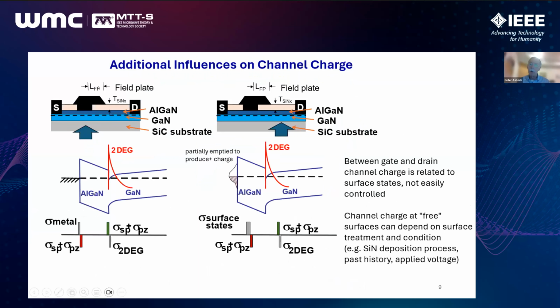But there's another consequence of the polarization charge formation that bears discussion. It's rather easy to see what goes on within the FET immediately under the gate metal. In general, however, there's a relatively large distance separating the gate and the drain. And here, the picture is a little bit less clear. Once again, there's positive polarization charge at the interface between channel and barrier, and associated with that, there's the 2D electron gas. But on the surface of the AlGaN, there remains the negative charge. And this is compensated for the most part by a deficit of electrons in surface states. But it's really the surface that controls the charge balance within this region.